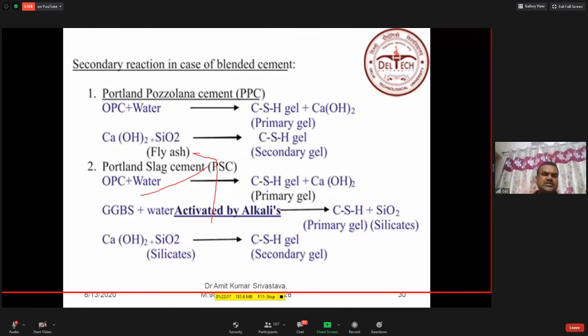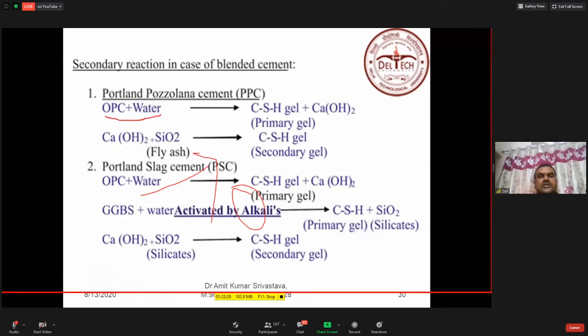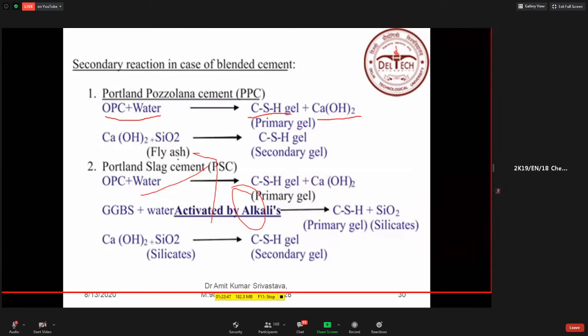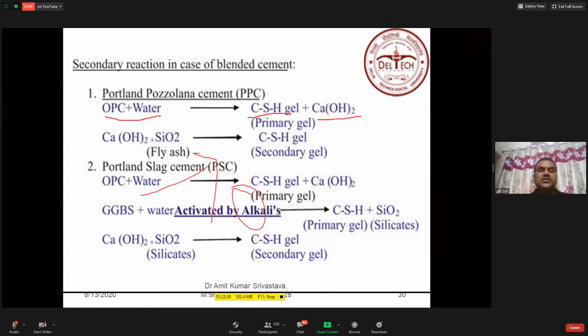Now what happens when we are using this type of material? You just see, when we use ordinary Portland cement and add water, it reacts and forms a gel called CSH gel, calcium silicate hydrate gel, and it leaves calcium hydroxide unreacted. So when we put fly ash, it contains silica. Just as I said, Indian fly ash has a very good concentration of silica. So this free lime, when it reacts with the silica, again forms a CSH gel, that is the secondary gel.